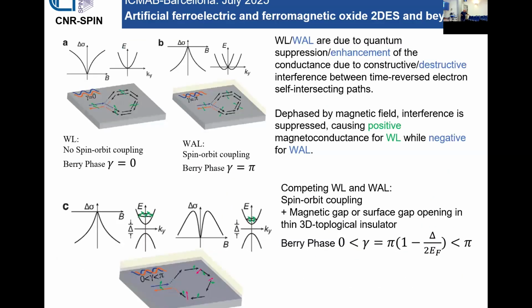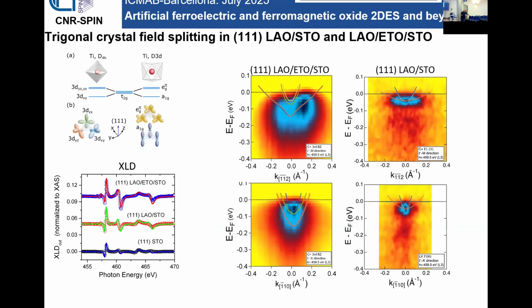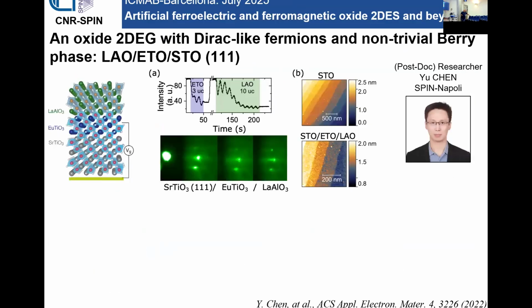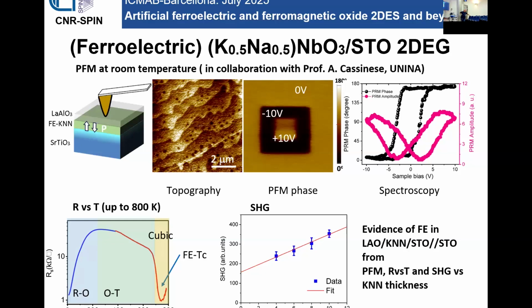Thank you for your talk. A question about the part on the combination between the interface of the two-dimensional gas and the ferroelectric that, if I remember correctly, was potassium sodium niobate. You have shown PFM results that, if we consider that this is due to ferroelectric switching in the niobate layer, it means that the polarization charge must be compensated by the two-dimensional gas when you go from negative to positive applied field, with either negative or positive charge in the two-dimensional gas. The question is if this is compatible with the scenario of polar catastrophe.